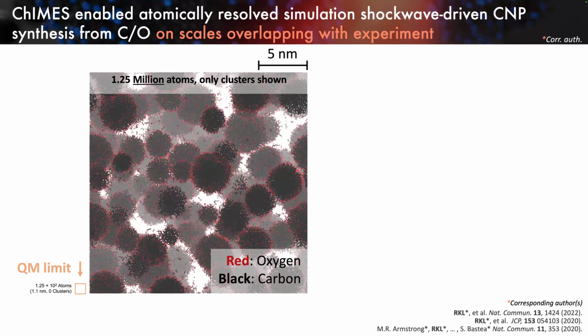What you are watching is the formation of a population of roughly 5 nanometer carbon nanoparticles with atomic resolution. So the short of it is that our simulations are predicting that yes, you can indeed use a shockwave to synthesize nanocarbon from a cryogenic liquid carbon monoxide precursor.